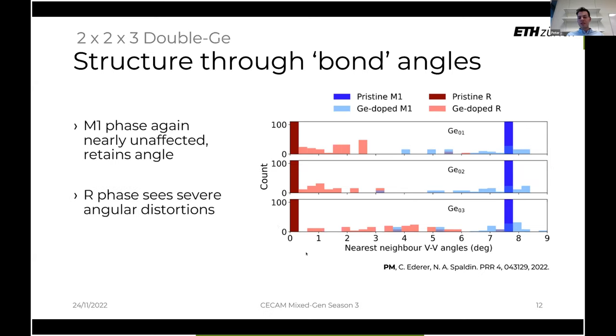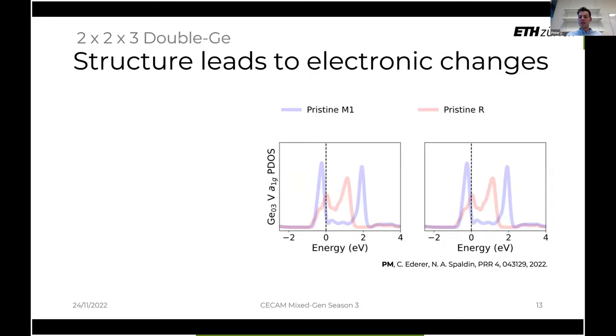And of course, these structural effects carry over into the electronic effects, where in the electronic structure, we are now looking at a particular configuration, the GE03 configuration, which was low in energy. We are particularly considering the projected density of states on the A1G orbital, which is the orbital along the chain. It is the orbital which is occupied the most in the monoclinic phase, and it tells you whether you have an electronically dimerized structure into a bonding and antibonding pair.